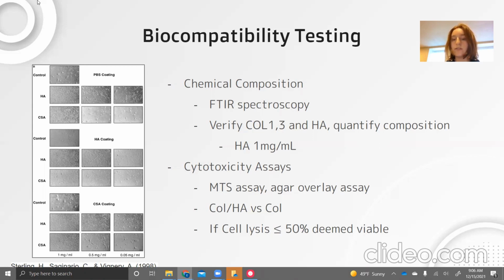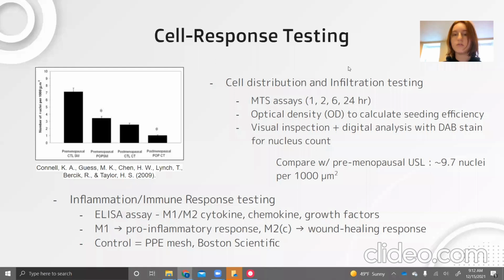And during these tests, if cell lysis is less than or equal to 50%, this would be deemed viable for cytotoxicity. Additionally, we would test the distribution and infiltration of the cells into the scaffolds using an MTS assay. The assays would be staggered over 1, 2, 6, and 24 hours, and the optical density would be used to calculate the seeding efficiency. Additionally, there would be a visual inspection digital analysis with DAB stain for nucleus count.